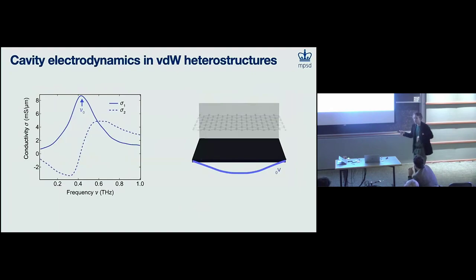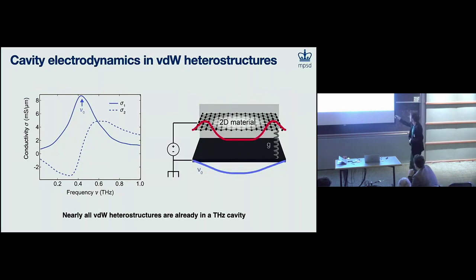Okay, so going back to this result, I just took a standard issue flake of graphite, the same kind of flake that the vast majority of van der Waals heterostructures are built on. This flake has a cavity plasmon resonance at 2 meV, exactly at the energy scale where all of these quantum phases are happening in the materials that are literally sitting 10 nanometers above them.